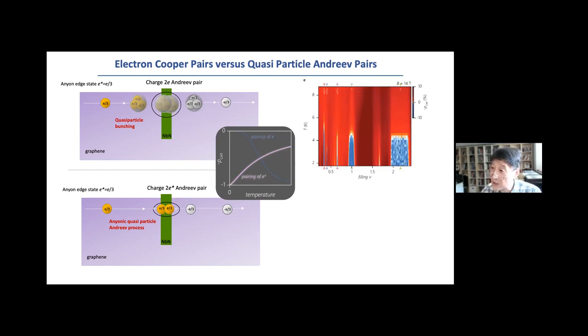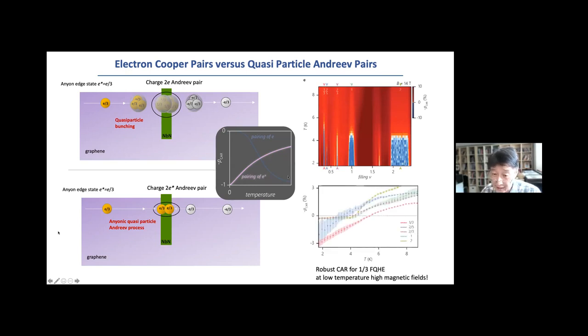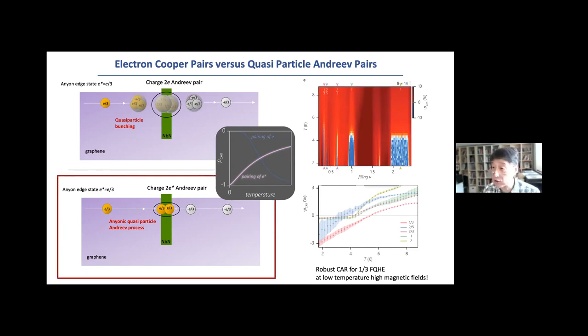Indeed, when we look at the temperature dependence of the CAR process, we found that the process, especially for 1/3 and 2/5, is stronger as you go to lower temperature, strongly supporting the idea of this charge 2E Andreev process. In other words, it indirectly proves the existence of parafermionic states in this type of system.